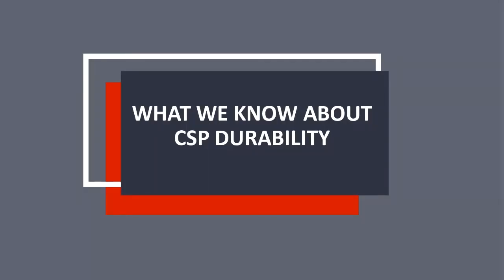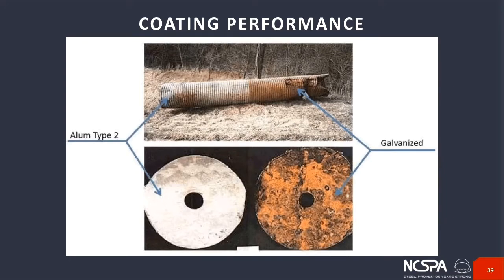How do we know as much as we know about CSP? Research has been going on this product for well over half a century. No pipe has been studied more in this regard. Now this picture illustrates the way two different coatings will perform essentially in the same environment, right? So you've got a galvanized material on the right-hand side, aluminized on the left-hand side. Clearly, the galvanized has suffered significantly through the life of this pipe. It's about 30 years old.